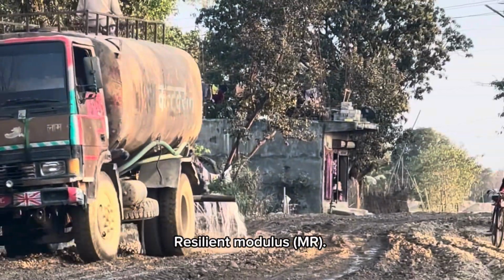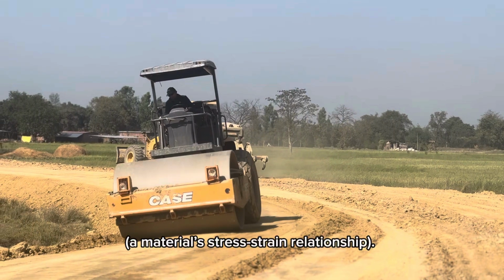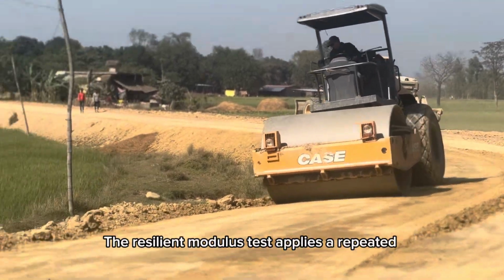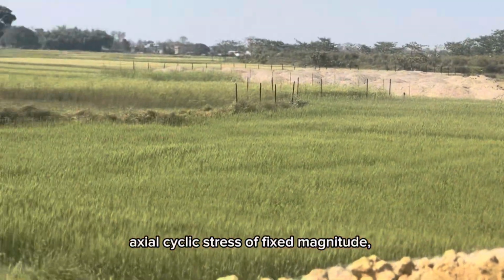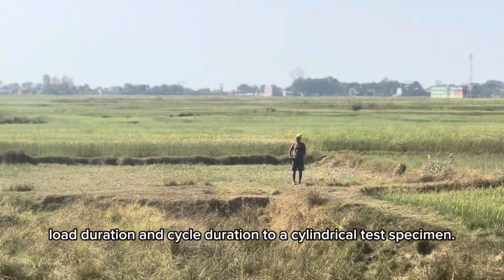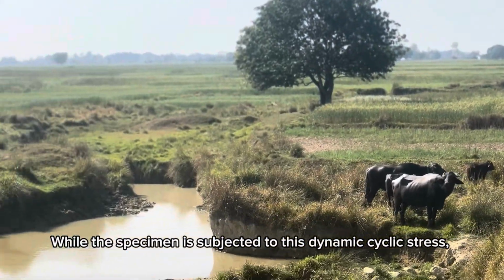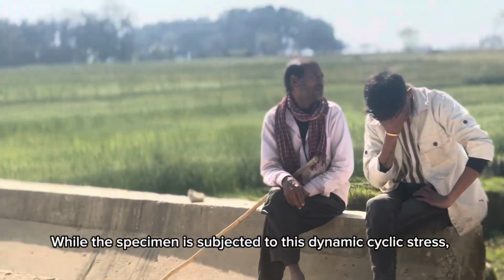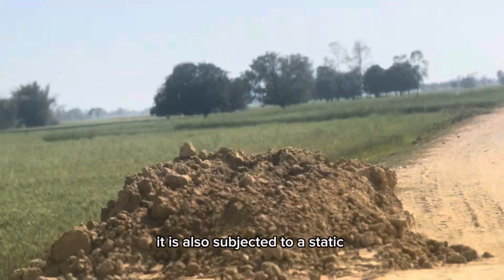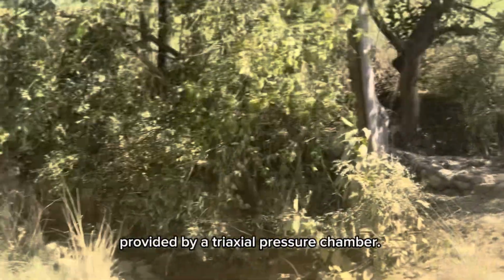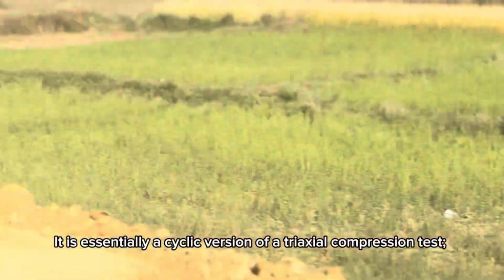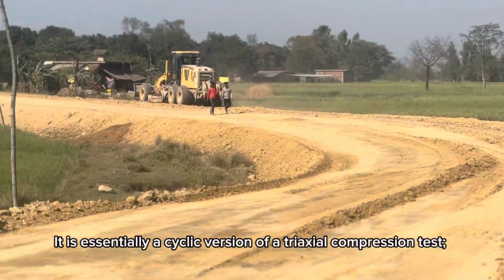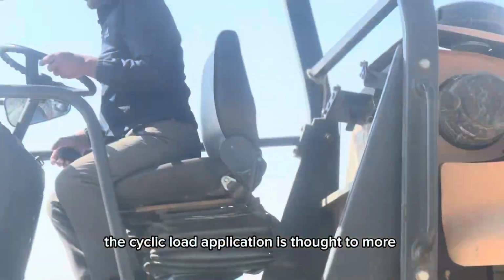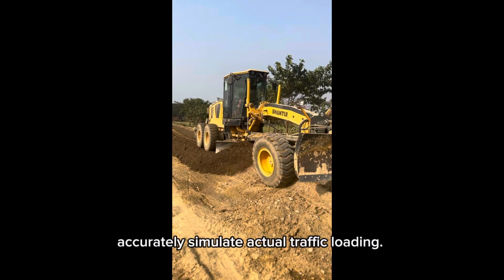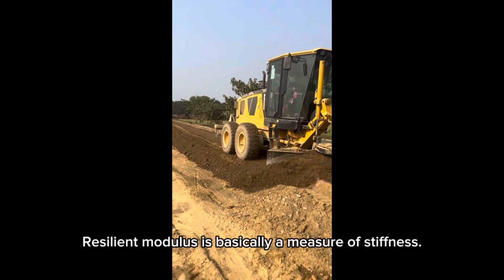Resilient modulus, MR, a test used to estimate elastic modulus, a material's stress-strain relationship. The resilient modulus test applies a repeated axial cyclic stress of fixed magnitude, load duration, and cycle duration to a cylindrical test specimen. While the specimen is subjected to this dynamic cyclic stress, it is also subjected to a static confining stress provided by a triaxial pressure chamber. It is essentially a cyclic version of a triaxial compression test. The cyclic load application is thought to more accurately simulate actual traffic loading. Resilient modulus is basically a measure of stiffness.